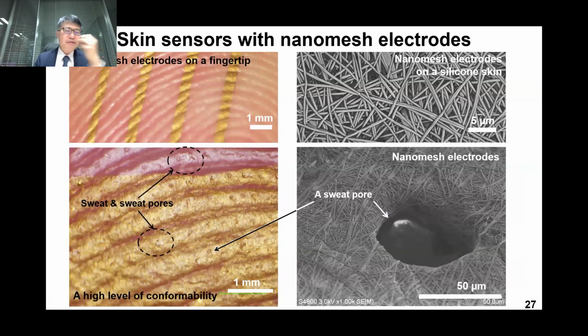The left photo shows the nanomesh electrode. The shining part is the nanomesh gold electrode, and it looks like a continuous film. But if we magnify the image by SEM, it obviously looks like a porous structure. Please look at the left lower figure. The shining part is the gold, the non-shining part is the bare skin, and the dark spots are sweat pores. If we look at those sweat pore regions, the same amount of sweat is penetrating both on the gold region and the non-gold region, which shows that the natural penetration and natural vaporization of sweat are not prevented by the nanomesh.